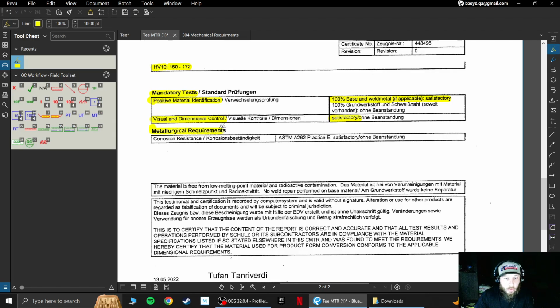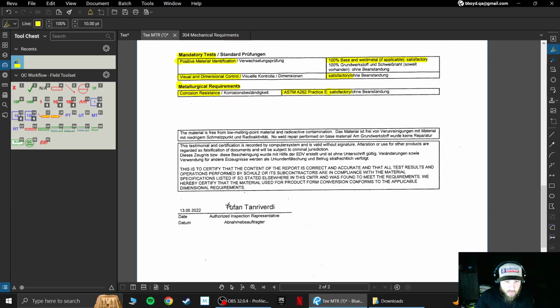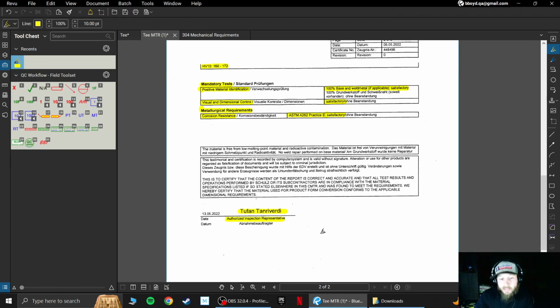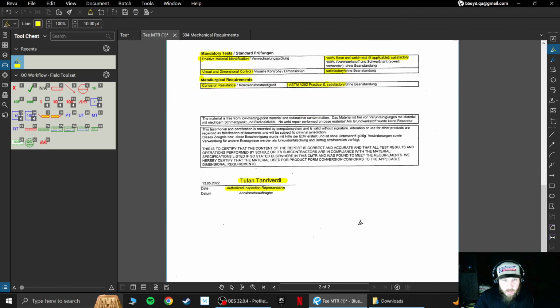So for metallurgical requirements, it shows corrosion resistance, and here it says ASTM A262 Practice E satisfactory. So Practice E means that they performed a Strauss test. This test basically just proves that the material was correctly heat treated and it meets all corrosion resistance requirements. Down here at the bottom, you'll see that it has been signed off by an authorized inspection representative certifying that this MTR is true and accurate. They give you the disclaimer right here above it, and that's pretty much it. So from what I can see, this MTR and this stainless 6-inch T is fully acceptable.